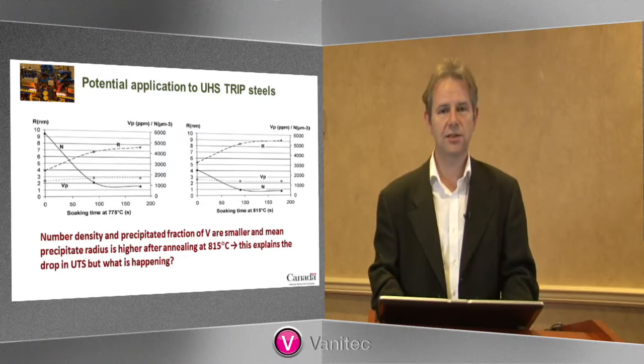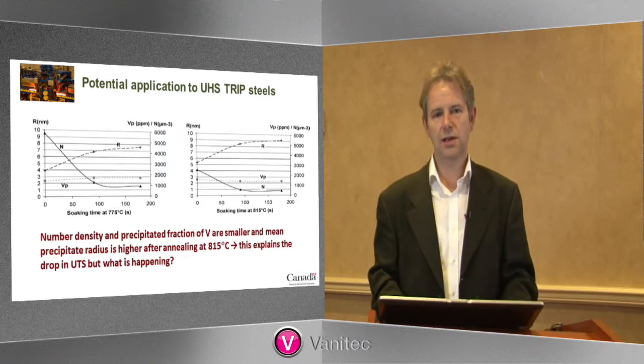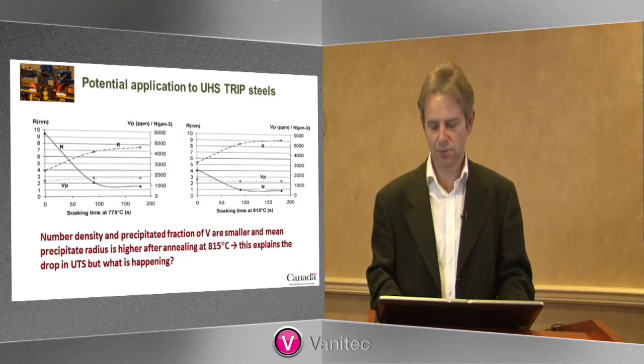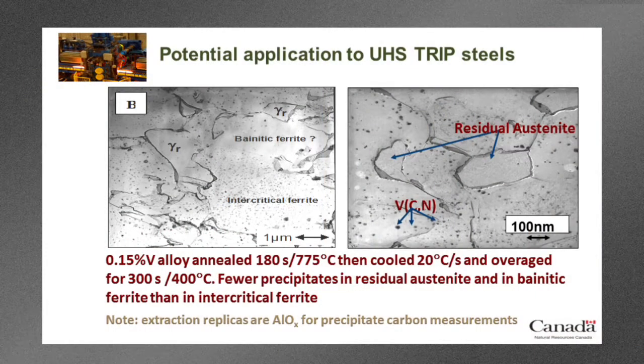So we actually did some interrupted quenching, and we tried to find out in the TEM how these precipitates were distributed between the ferrite and austenite phases. And it's actually very interesting. This image here is the final microstructure. So we've gone through 180 seconds of intercritical annealing, and then we cooled it at 20 degrees C per second and overaged for 300 seconds at 400 degrees C.